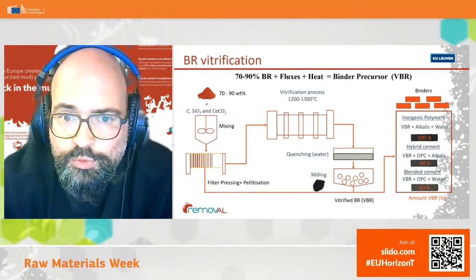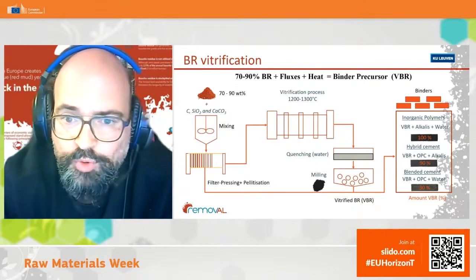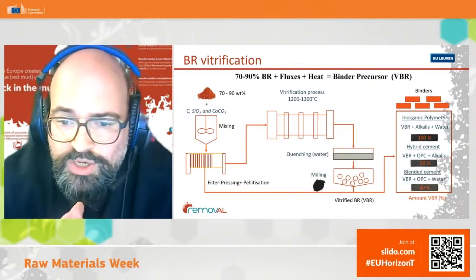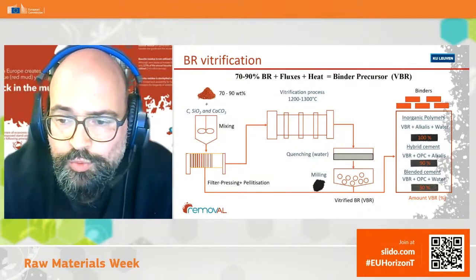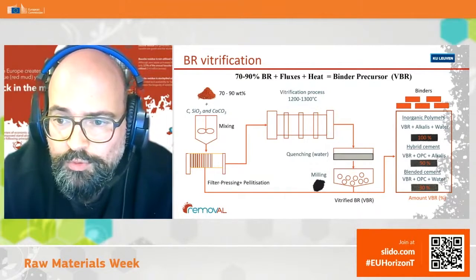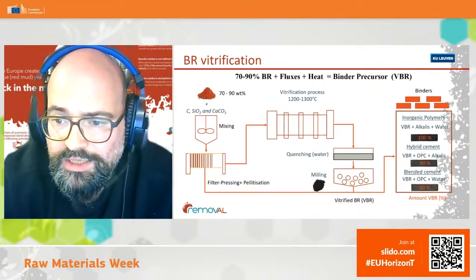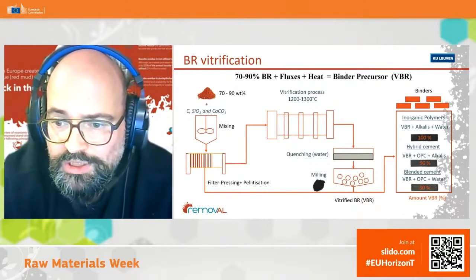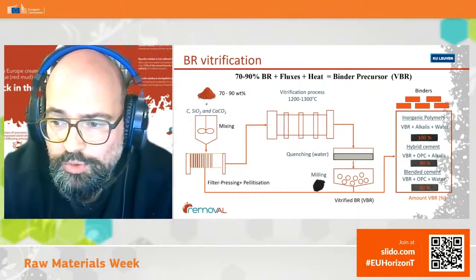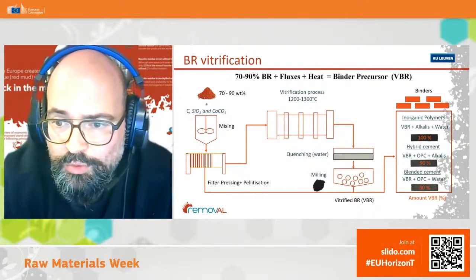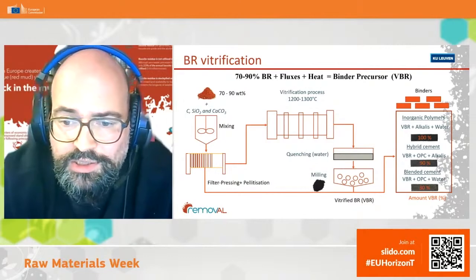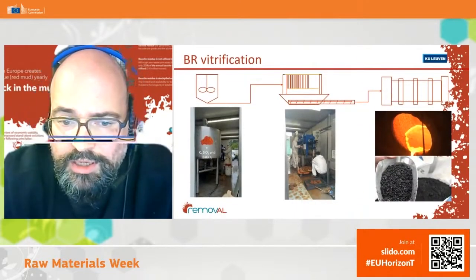In KU Leuven, another technology has been developed where they take bauxite residue, mix it with fluxes, and do a heat process to vitrify the bauxite residue and then mill it in order to create a precursor for different types of binder systems. So you can use that in a hybrid cement if you mix it with OPC and water. You can use it in a sort of geopolymeric cement or even in geopolymers. Next slide.